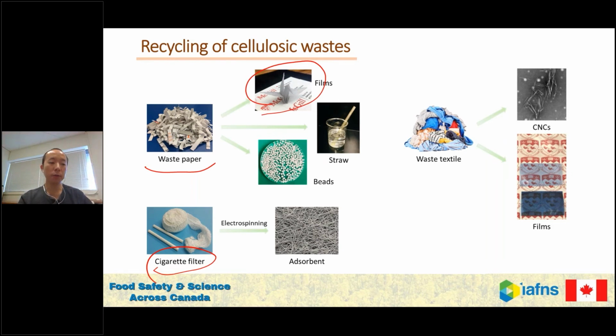And we can also use a cellulose solution to make something like a straw. This straw is more like a plastic. It's different from the paper straw you see in, like, A&W. This one looks like a plastic and it's quite stable in water. That's our student project. And we also use waste paper to make beads. Those are cellulose hydrogels with porous structure. So we can use those beads to retain water, for example.